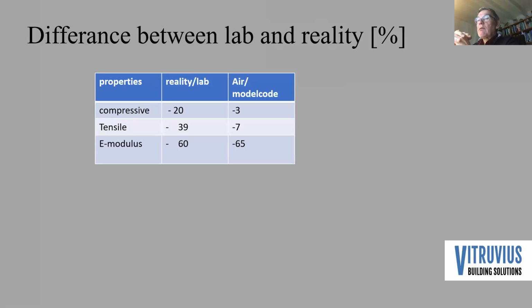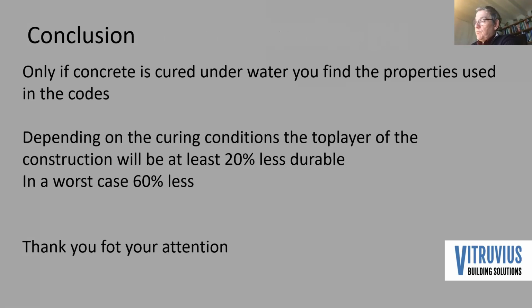If you look at the difference between the two realities, you see that depending on the condition, on what you are measuring, compressive, tensile or E modulus, the difference is between 20 and 60% lower if it is air cured. Next, please. So only if concrete is cured underwater, you find the properties used in the codes. And depending on the curing conditions, the top layer of a construction will be at least 20% less durable, and in the worst case, 60% less than what you expected. Thank you very much for your attention.